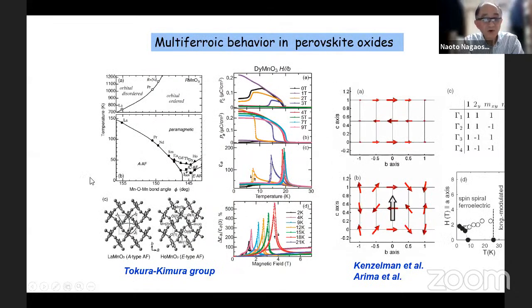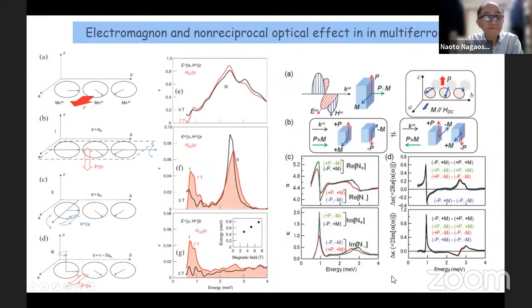And actually, this is one example for the proof of this mechanism, in the case of dysprosium manganese oxide. And in this material, there are two phase transitions. First, you have this collinear spin structure, and there is no polarization. But at lower temperature, you have a second phase transition, which transforms from collinear to non-collinear cycloidal magnetic structure. And then you have a polarization along this direction, which is consistent with this formula.